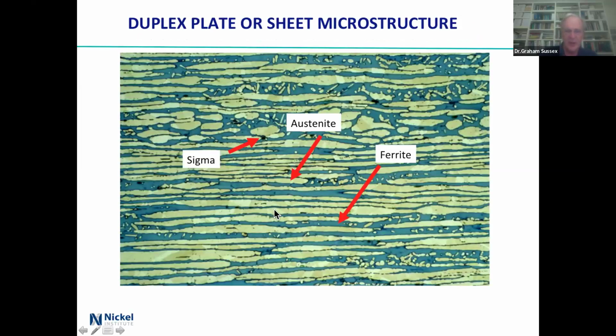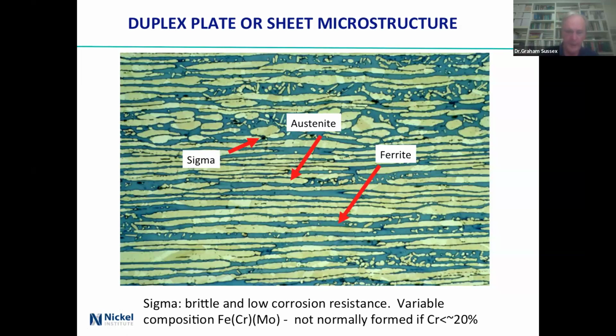This is a cross section. Here we're looking at a cold rolled piece of material, ferritic from where it actually originally solidified, and the austenite has grown out and then been rolled out flat like this. And unfortunately, at the grain boundaries, because there was a bit of a problem somewhere, you've got sigma phase forming, these little black specks. There's not a hell of a lot of it, and that may actually be not enough to worry about, but it's something that would be picked up and reported. Yes, I've already said sigma is brittle, low corrosion resistant.